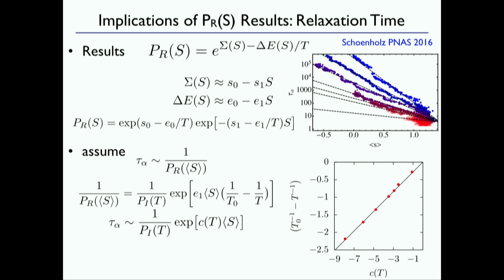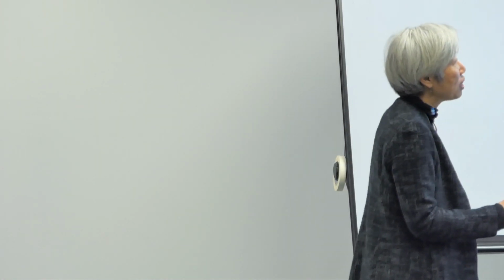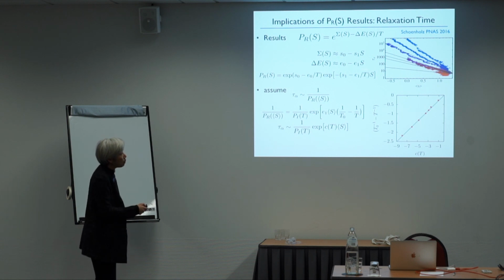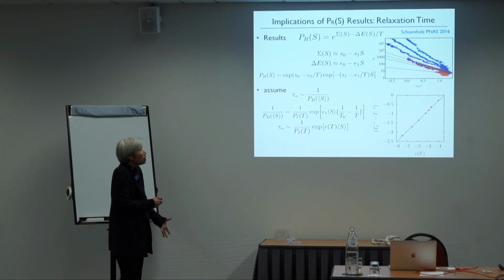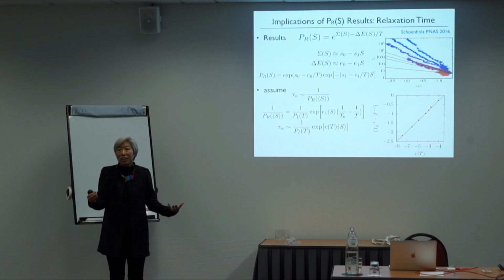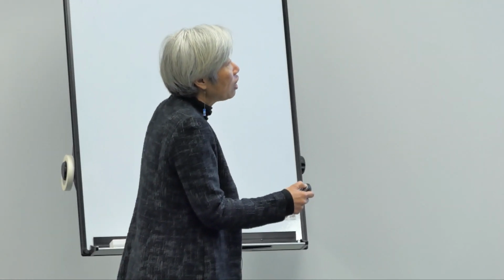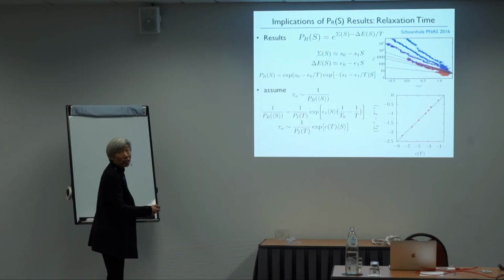So now the relaxation time itself. I showed you there was this relation between the relaxation time and the average softness. So let's just make a very simple assumption. We have these two pieces, the softness independent piece and the softness dependent piece in the probability of rearranging. Now let's assume that the relaxation time is 1 over the probability of rearranging evaluated at the average softness. You take that, you stick that into here, you work that out, and you see that the relaxation time is exponential in the average softness, with a coefficient which should go like 1 over the onset temperature minus 1 over the temperature.